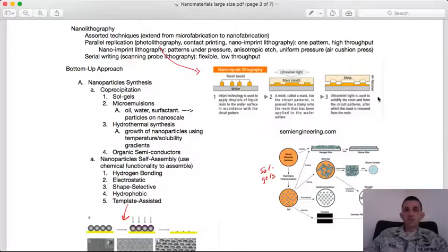So you can reproduce that pattern, not through changing chemically with UV light certain regions by having opaque and transmissive regions on the mask, but here you have different thicknesses. So if you come in later with an anisotropic etch, say like an ion etch, you're going to etch away the thin parts of the photoresist before you etch away the thick parts, and that allows you to reproduce this pattern.